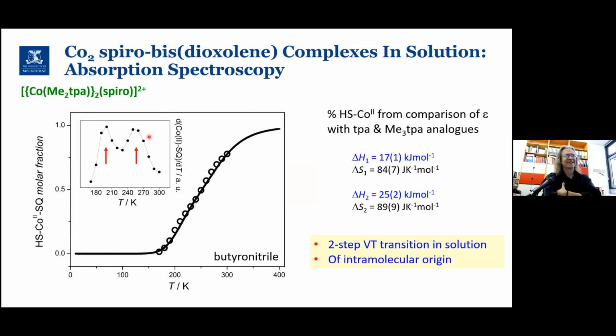Wow. So we think, all right, it's not super duper conclusive, but we do think that we in fact are seeing a two-step VT transition in that solution. And if it is the case that it is in solution, then that makes it very clear that it's of intramolecular origin. It's not to do with crystal packing or any of those types of effects. So we think so. And the DFT is consistent with that. So I think that's reasonable.